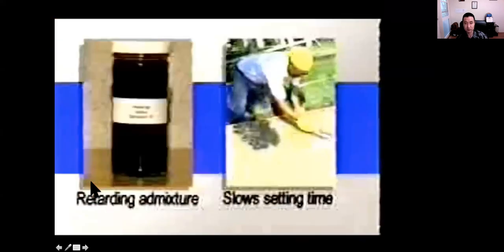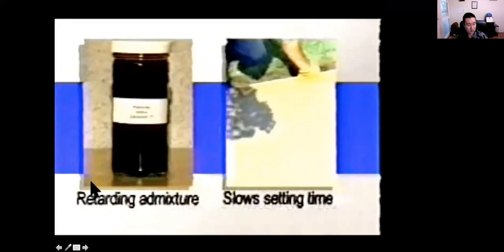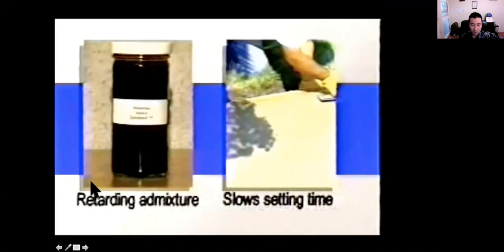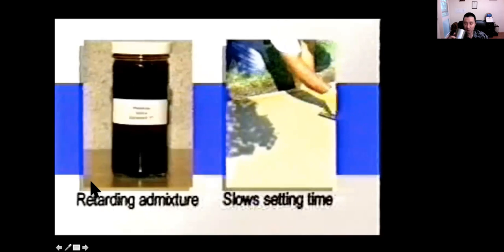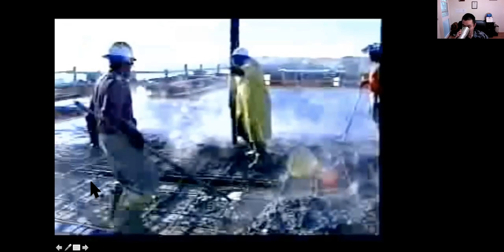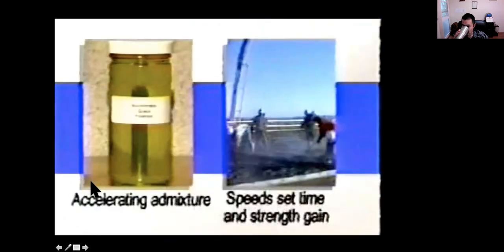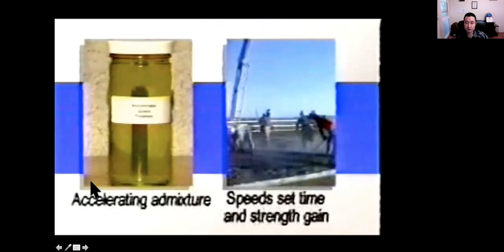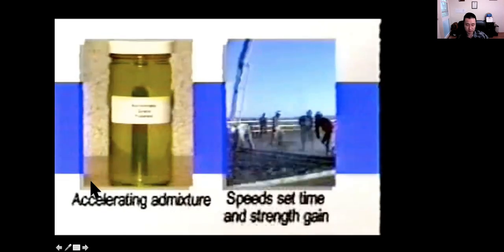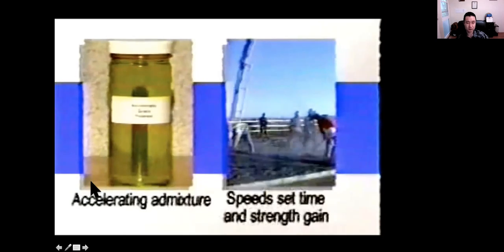To slow setting time and minimize cracking in hot weather, a retarding admixture should be added to the mix. In very cold weather, hydration and strength gain may slow or stop completely. To place concrete for this high rise in winter, an accelerating admixture may be needed to speed the concrete's set time and strength gain.